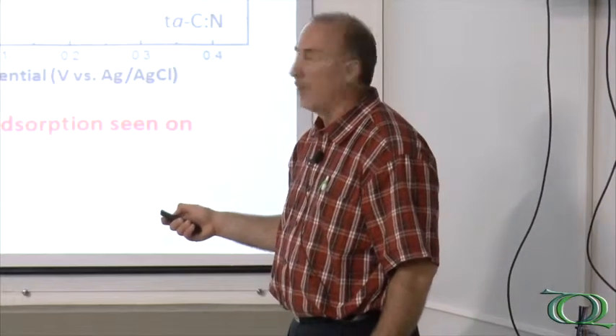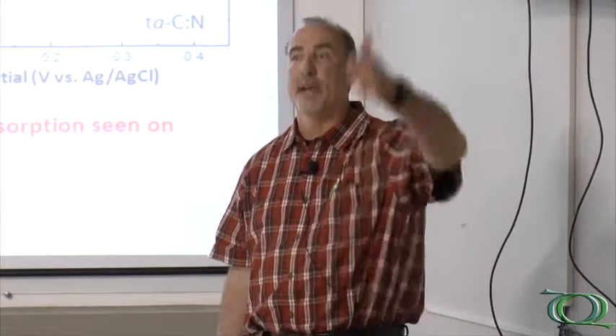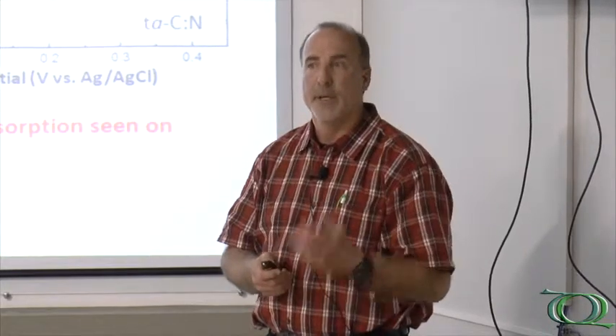If you do the same experiment on glassy carbon, the waveform changes quite considerably. You see sharp symmetric oxidation-reduction waves, very characteristic of adsorbed redox-active processes. The measured peak current here is 7 microamps, whereas theoretically it should be 0.15 microamps for a diffusion-controlled system. So we have many molecules adsorbing onto the surface. This kind of experiment with strongly adsorbing molecules gives you a very good idea about the microstructure of your material. Even though TAC films have some sp2 bonded character, the bonding is not graphitic and doesn't promote strong molecular interactions with molecules like methylene blue.